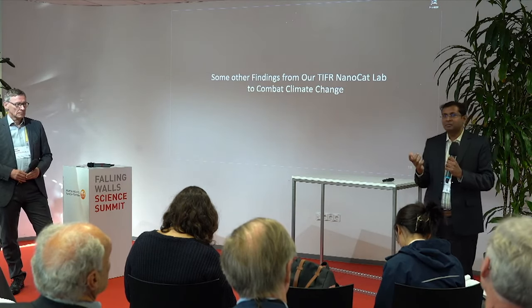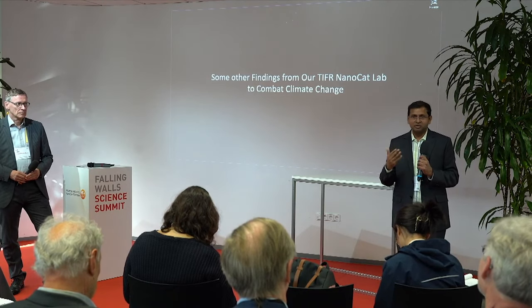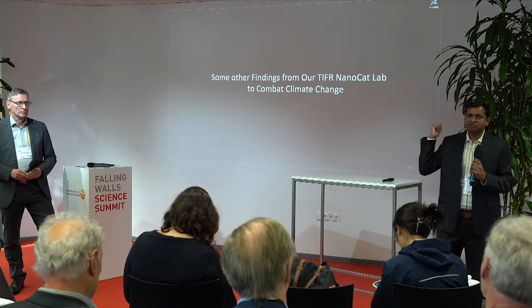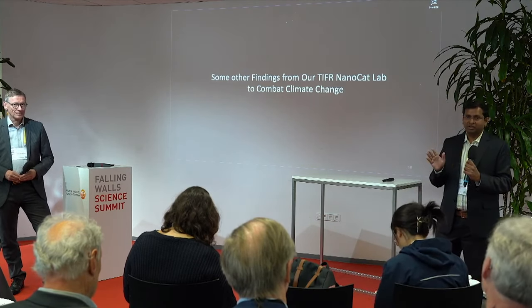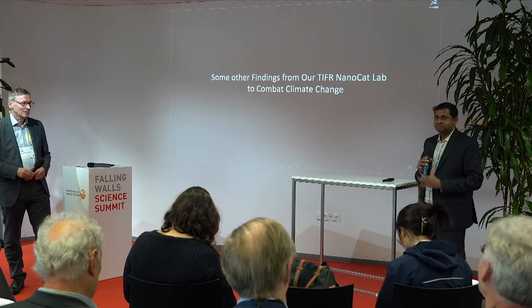And we're not blocking the pores because it's happening at a lower temperature. Ideally, you're not giving any temperature. It's just light. The natural temperature that it produces is around 200 to 250 degrees Celsius. So there's no carbon formation, and so there's no blocking. We showed it to you for 100 hours. There was no blocking of any pores or active sites.